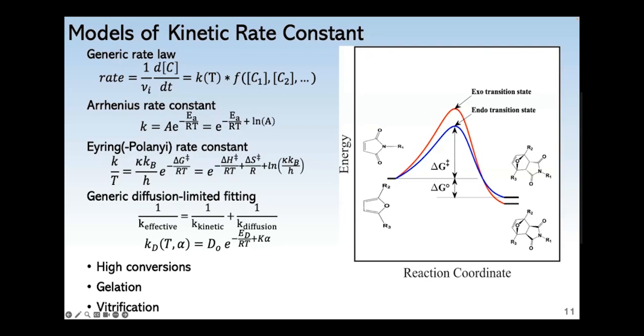Okay, and for polymers in particular, reaction rates become not just a function of the reaction timescale, but also the diffusion timescale for the reactants to get close enough for the reaction to occur. And in liquid state reactions, this only usually becomes apparent after you've reached really high conversions. But in polymers, you also have gelation and vitrification that can occur. Gelation, in a sense, will cage your reactants, and then they have to diffuse around in order to form a new bond. But all polymers will also eventually, or at low enough temperatures, turn glassy or vitrify. And this is where individual chains or segments lose their translational motion, and that will freeze over any additional reactions that can occur.